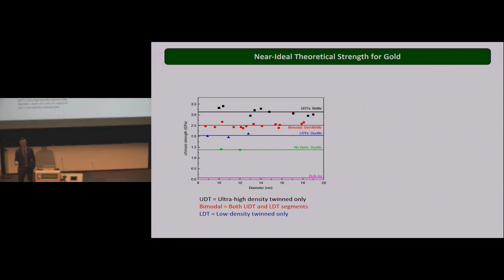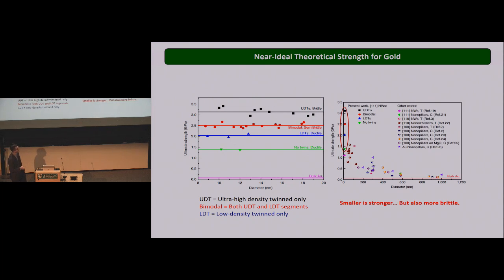Of course, we wanted to make sure everything was consistent with the experiment, so we were able to reproduce many tests showing distinctive behaviors in the experiment, and we plotted our result against the literature result for gold, and I believe we still have the world record in the strength of gold with this type of design, having nanowires with twin boundaries. So that was the discovery.